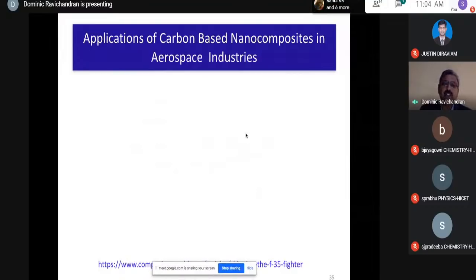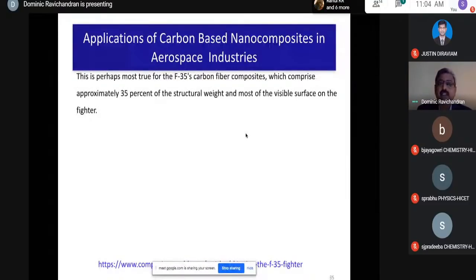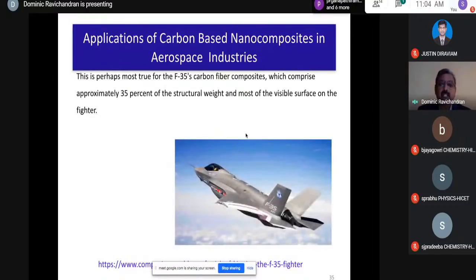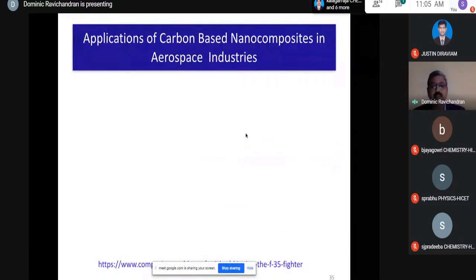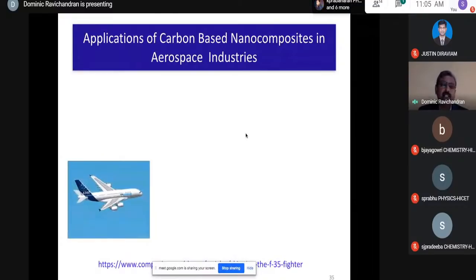In case of the aerospace industry, even in the F-35, the carbon fiber composite is used, where 35% of the structure in the fighter plane F-35 is a carbon composite. The carbon composites used in these fighters are kept confidential because it is patented, so they don't reveal what composition they use, but they say that 35% is made of composites. And in case of Airbus A380, again, the wings and other parts are made by carbon-based composites.